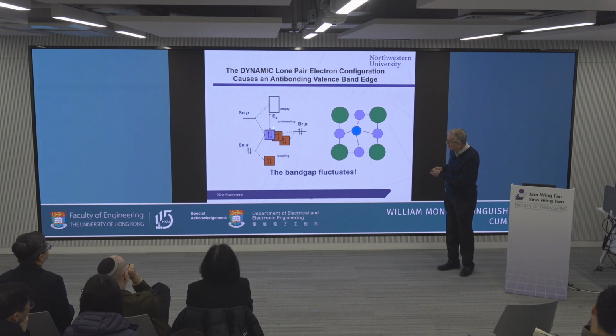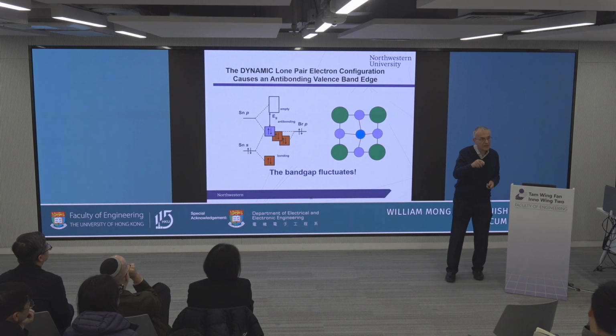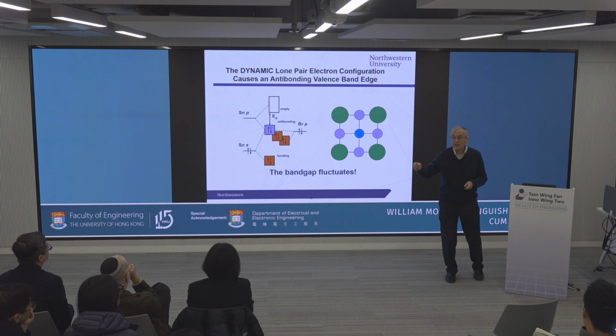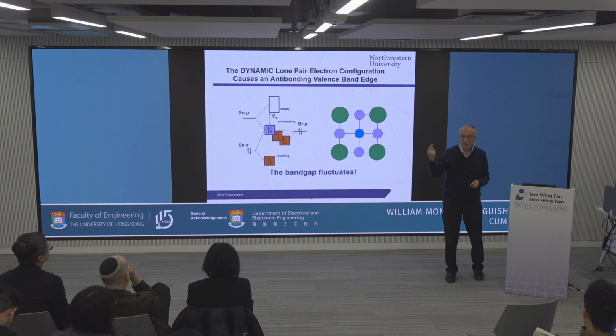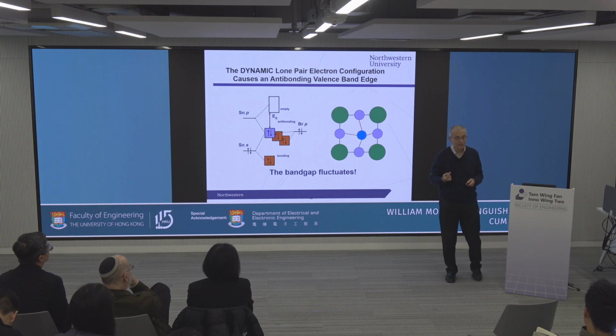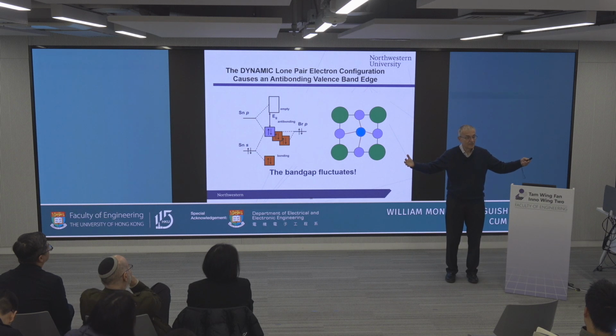if you excite electrons all across this gap, within a few picoseconds, the lattice is different because it has changed. Within a few picoseconds, the electronic structure is different. They're trying to recombine naturally. They're trying to find each other. But because the electronic structure is slightly different, it takes them a while to find themselves. And it delays recombination. That lengthens the lifetime to the hundreds of nanoseconds. That means they live long enough to collect them. They move around in the field. They have long diffusion lengths. They don't recombine. You can recollect them.